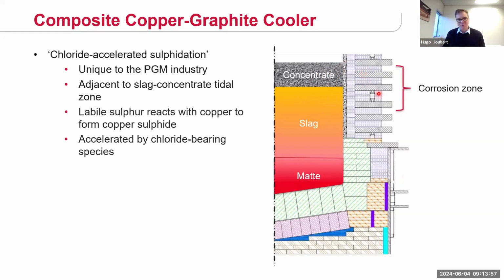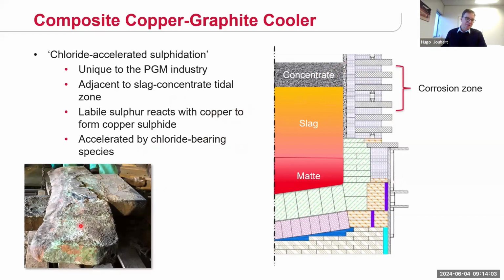And it's also been found to be accelerated in the presence of chloride-bearing species. So this photo shows a plate cooler from furnace number 2 at Sibanye after 27 months of operation. And you can see how it's been corroded away, especially on the hot face, formed almost like a knife edge. And you can just imagine what this does for the thermal contact between the cooler and the surrounding brickwork, and it just completely takes away any of the cooling efficiency.